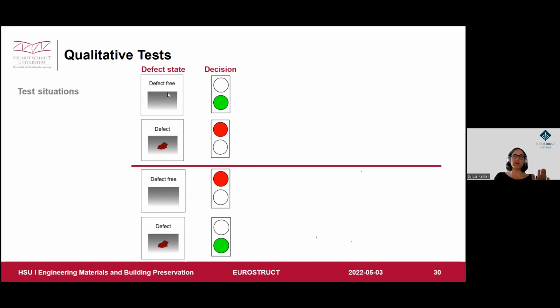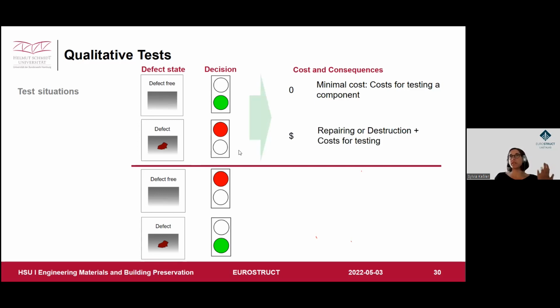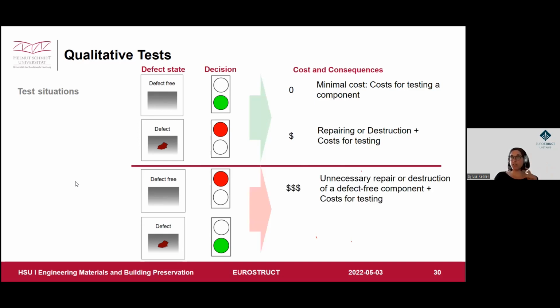Normally, if you have a defect-free structure and we decide that it's defect-free, so corrosion-free, it's okay. We have no costs and just costs for the inspection itself, but the asset owner can be happy. If we have a defect and we detect the defect, or we detect corrosion, it's okay. We have repairing or destruction or cost for testing. Here now comes the much more severe situation. We have no defect, but we detect a defect, so we detect corrosion, so unnecessary repair. And the worst case would be that we have corrosion going on, but we do not detect it, which could lead to very severe consequences.